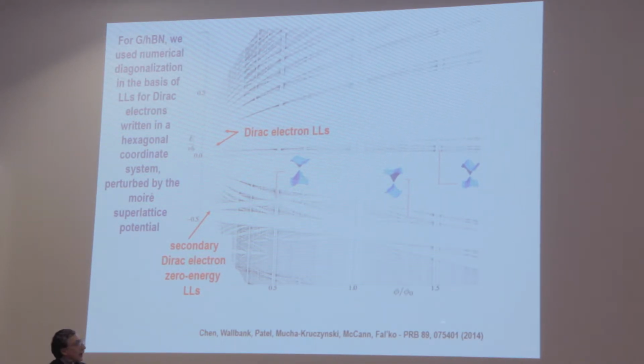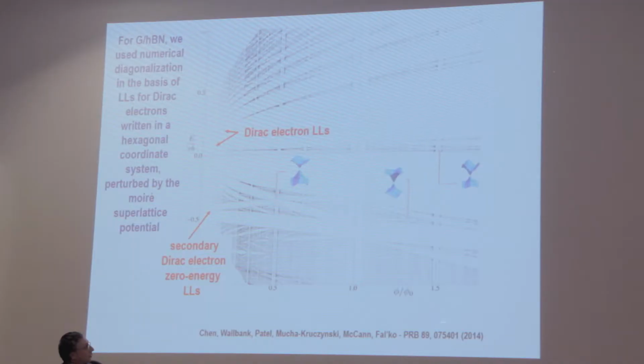potential that I described in one of the previous slides to diagonalize numerically and to get the spectrum of the system. So I plotted it here in the same way as in the Hofstadter butterfly spectrum, that the ticks indicate the energy intervals where we get the states as a function of the value of magnetic field flux piercing the unit cell of the superlattice. And we can track some of the groups of the states to the Landau levels of Dirac electrons, which you can see coming up together in the small range of fluxes, therefore small magnetic fields. And also you can track the groups of the states coming into what looks like the zero energy Landau level of the second generation of Dirac electrons, which appear at the edge of the first miniband due to the Moiré